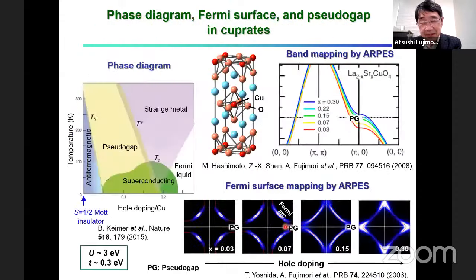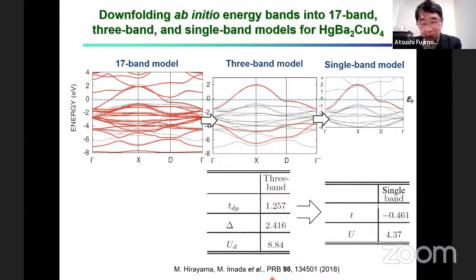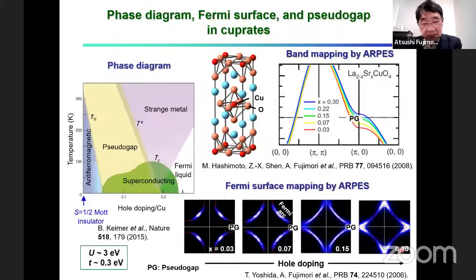And interestingly, those parameters turn out to be similar to the spectroscopic values: very large U, charge transfer energy of a few eV, and a hopping integral of 1 to 1.5. But in the single-band model, U is reduced and the hopping integral is also reduced, consistent with the generally used single-band parameters.